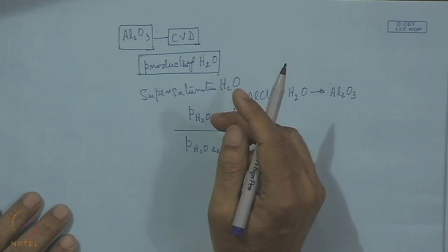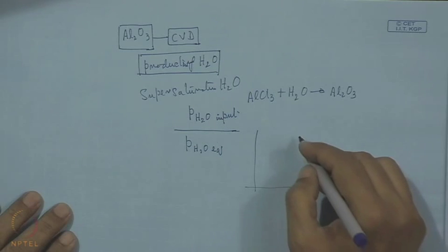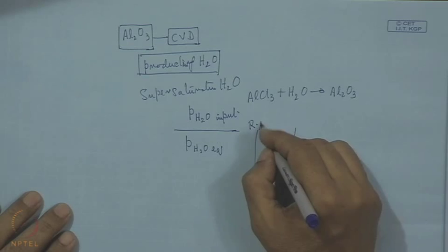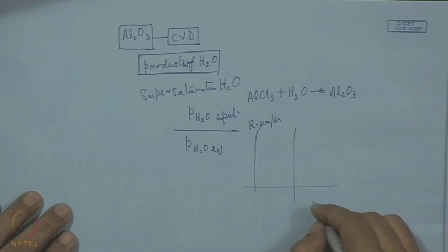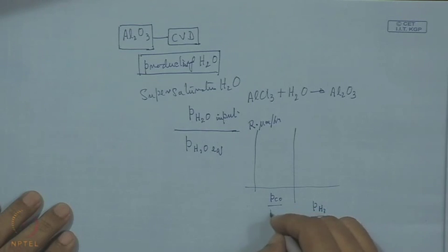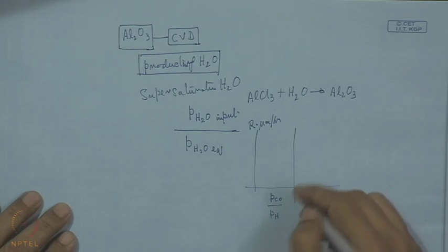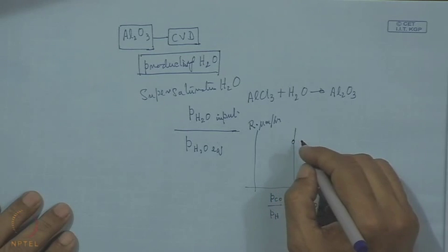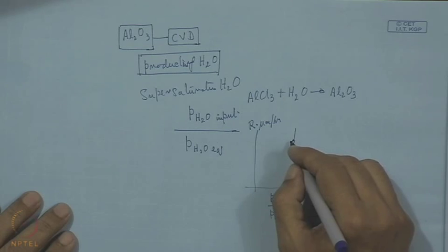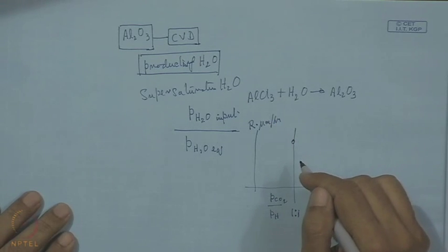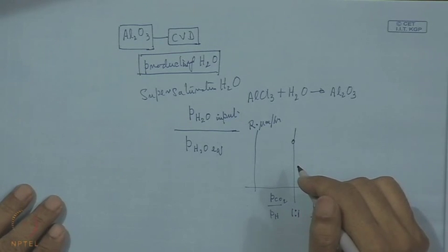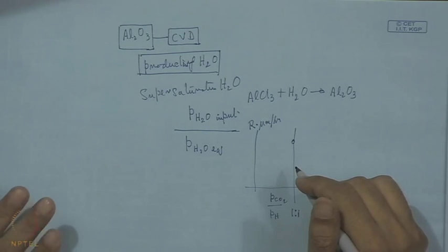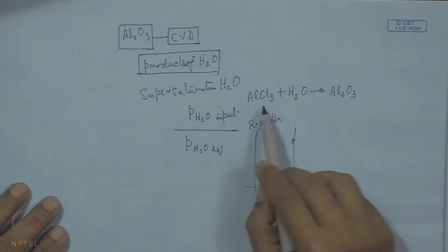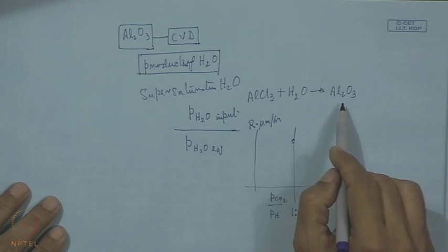Now, this is actually the effect of the pCO2 and pH2 ratio, but it can also be shown this way. This is the yield R, in micron per hour, and here we have pH2 by pCO2, and on this side we have pCO2 by pH2. Obviously, when it is 1:1, we have the very high value, and on both sides we have a decreasing trend in growth rate. So, this ratio should ideally be a 1:1 partial pressure ratio to have the highest production of H2O, and this will lead to a faster growth rate of Al2O3.